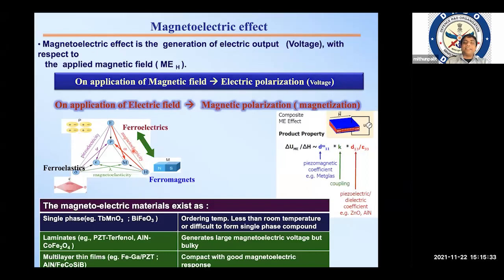Well, this magnetostrictive material alone cannot be used as some kind of sensor. So we have used a concept called the magnetoelectric effect, wherein basically you can produce a sandwich between a ferromagnetic material and a piezoelectric material. The ferromagnetic material demonstrates magnetostriction; as it expands or contracts, it produces some stress on the piezoelectric material, and you can produce some voltage by that. Basically, you can use it as a magnetic field sensor or something of similar application. So we can see over here that Terfenol and some piezo composite, so Terfenol is the TbDyFe material, works out to be the better.